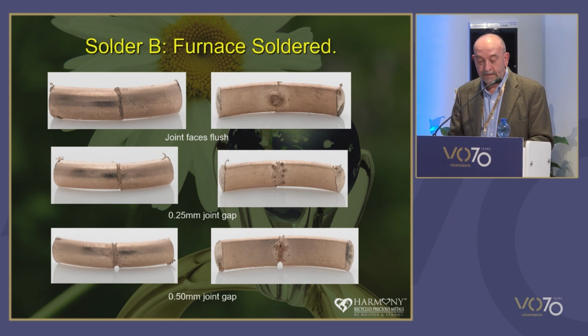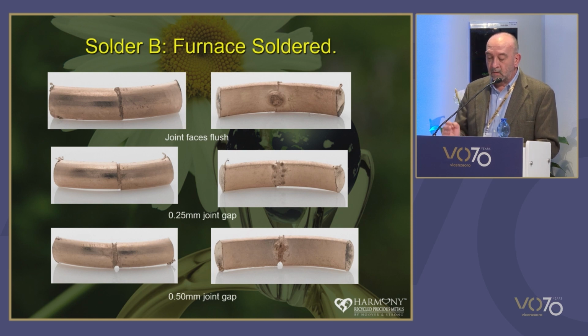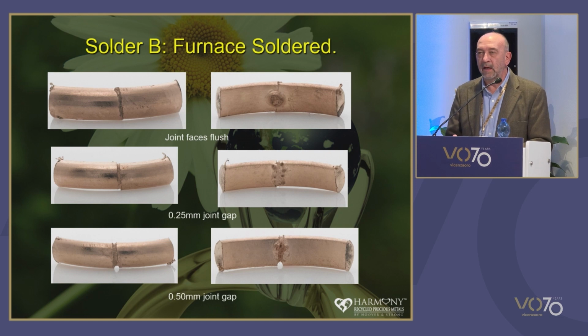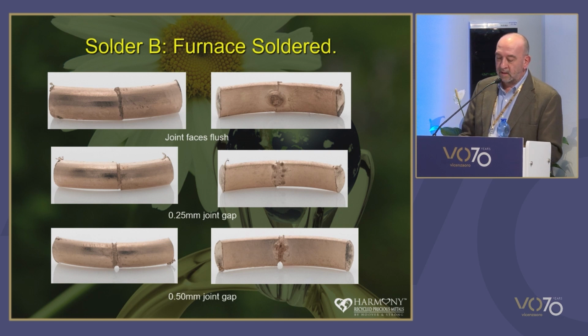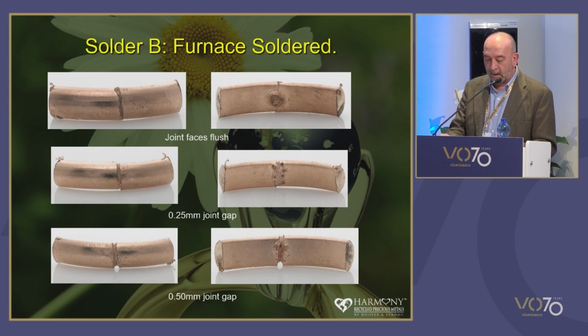So the 4th test we did was to solder a post on top of a cup setting to make earrings, and this is a textbook example of a T-joint. We used the same test criteria for torch and furnace soldering, and we tack welded the post on top of the earring before applying any solder.